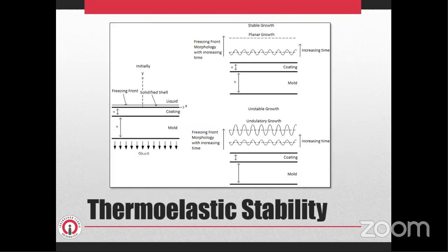These non-uniform undulations occur as a consequence of the non-uniform heat extraction along the shell mold interface. If the heat extraction across the mold is uniform, the solidified shell is grown planar to the end of the process. But physically, this is not possible due to the thermal and mechanical events occurring during solidification. Therefore, some non-uniformities are added to the extracted heat.